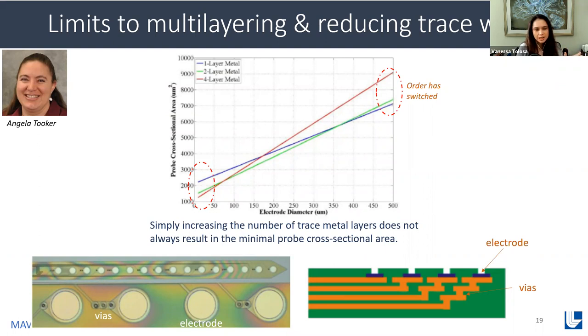But as the electrode size gets bigger, so going to the right, the benefits of stacking diminish such that the optimal number of layers is actually 1, not 4. And this is true only in the kinds of designs that we were doing at the time, where we were using vias to interconnect the layers, with each layer having to take up space with these vias that I show here on the bottom left. And a lot of this work was done by my colleague at Livermore, Angela Tooker.